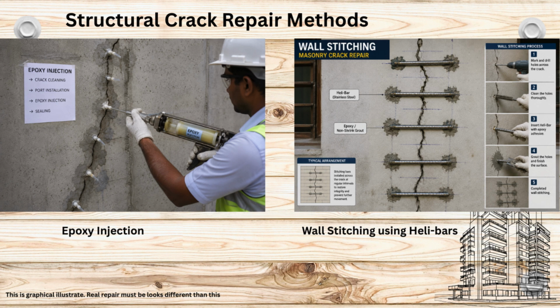However, if reinforcement corrosion is already severe, simply injecting epoxy or stitching the wall may not be enough. The damaged concrete must first be removed. The exposed reinforcement is then cleaned, treated against corrosion, and rebuilt using approved structural repair mortar. Every structural crack is different. For this reason, the repair method should always be selected by a qualified structural engineer after a proper inspection.